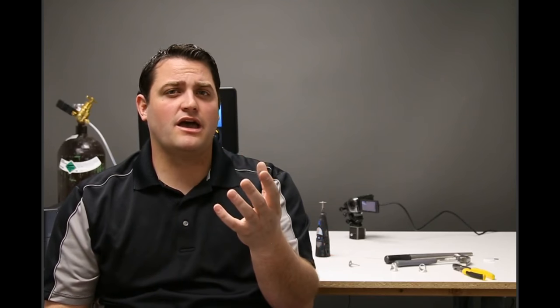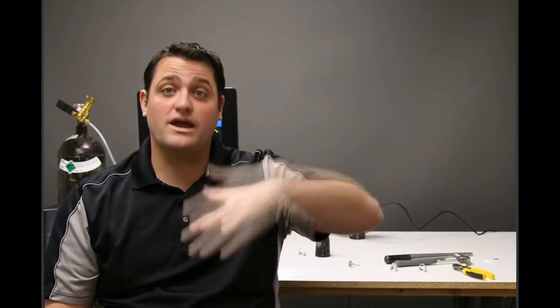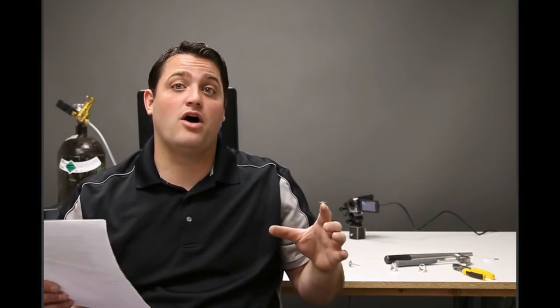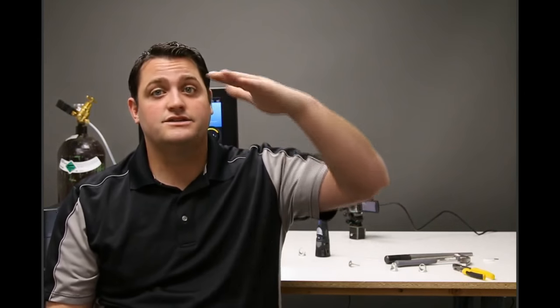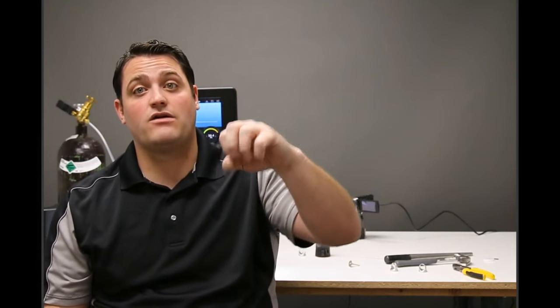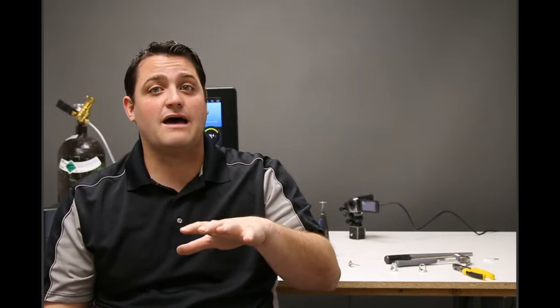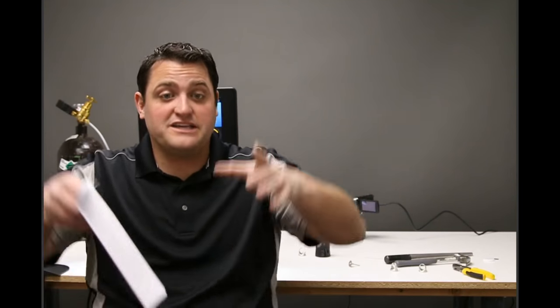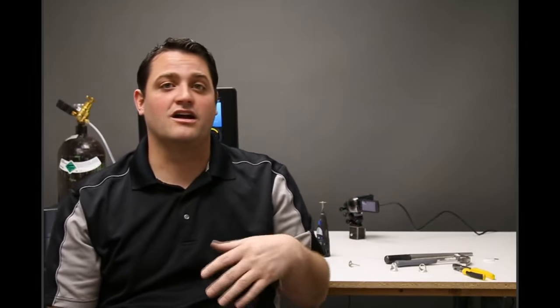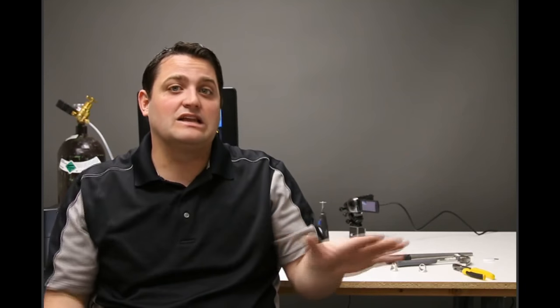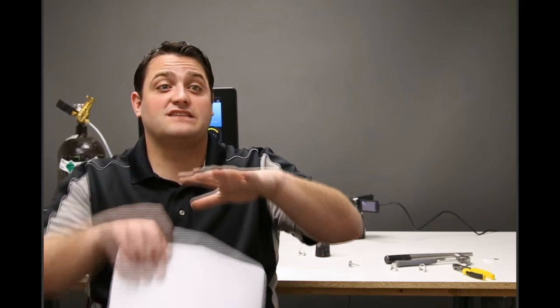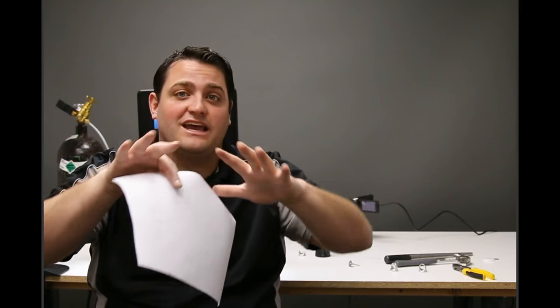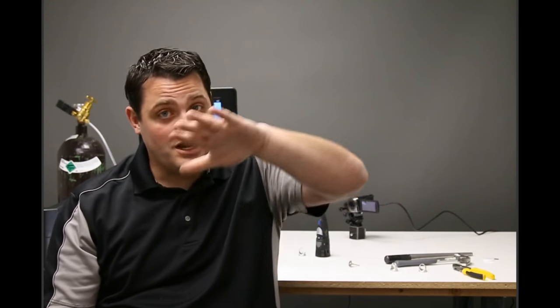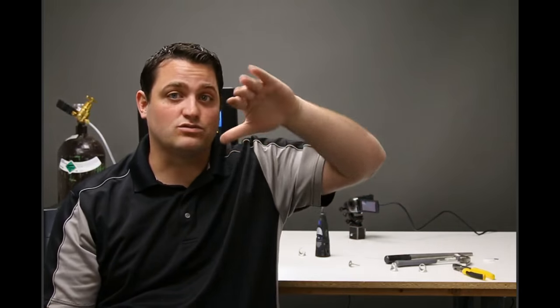Like I mentioned before, the longer the weld time, the smoother it works. Basically how this principle works is if you imagine that we're throwing a rock in a pond, it's going to create ripples. As soon as we throw that rock, obviously we're going to have a big splash. And if we froze that pond that we threw our rock into, we would have a big splash and create a little bit of a crater. But if we allow that pond to settle a little while and then we froze it, what we're going to see is that that crater has been allowed to flow back in and flow together again, and have much less ripples in that weld.